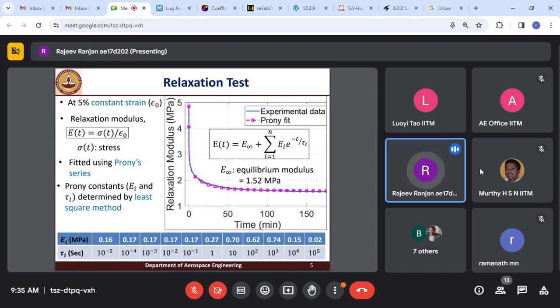Since the composite solid propellant is a viscoelastic material, relaxation modulus is an essential mechanical property. In order to get the relaxation modulus, a relaxation test is conducted at 5% constant strain. To reach that 5% strain, a high displacement rate of 500 mm per minute is considered. This is because the relaxation test is the response of the material to instantaneous deformation. Then at this 5% strain, the specimen is held for 180 minutes, and the decrease in force with respect to time is recorded. Then using that force, stress is determined, and using this formula, relaxation modulus is determined.